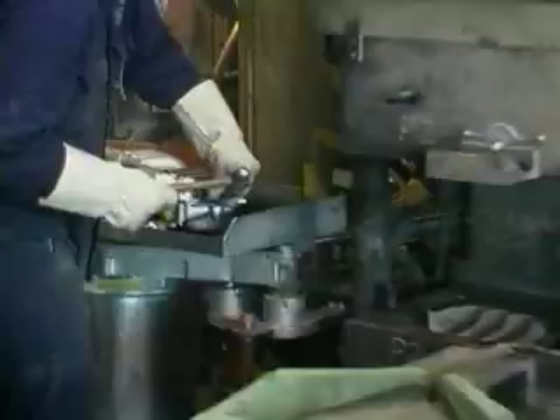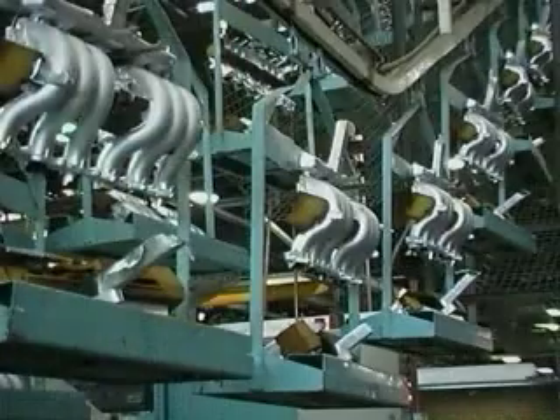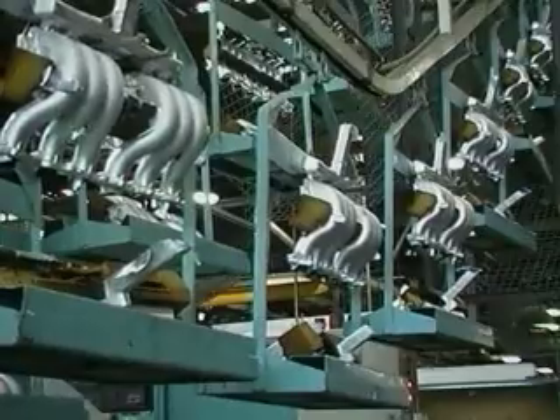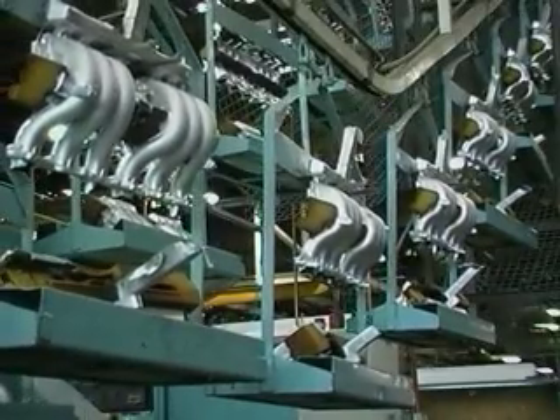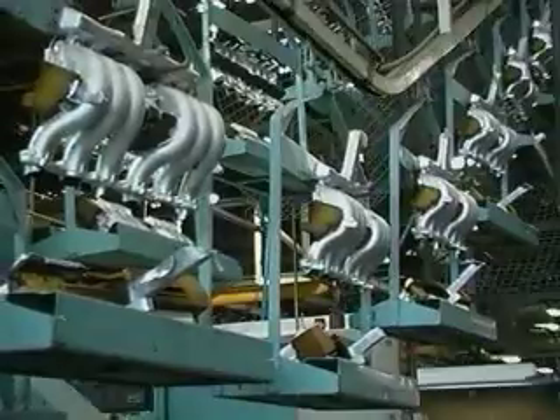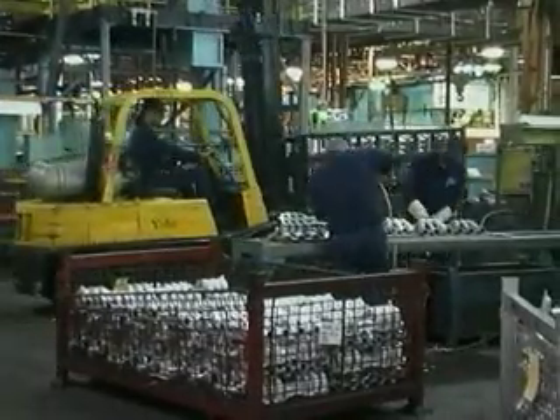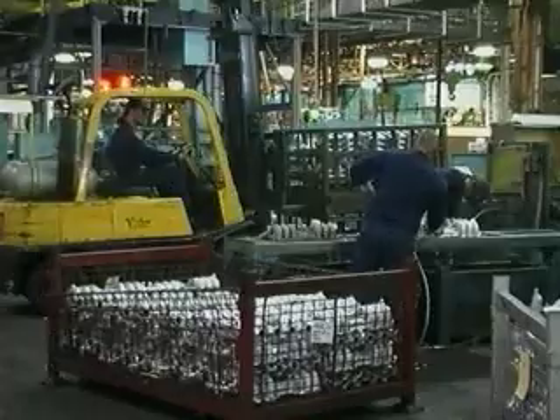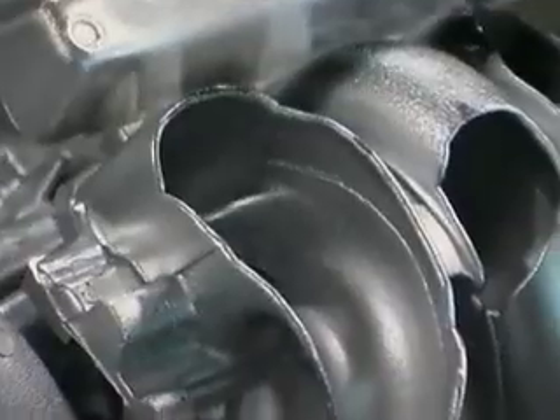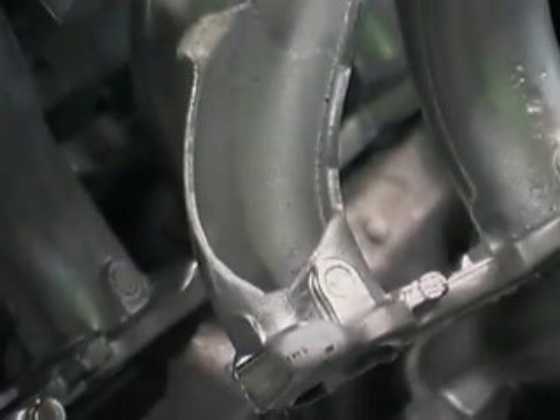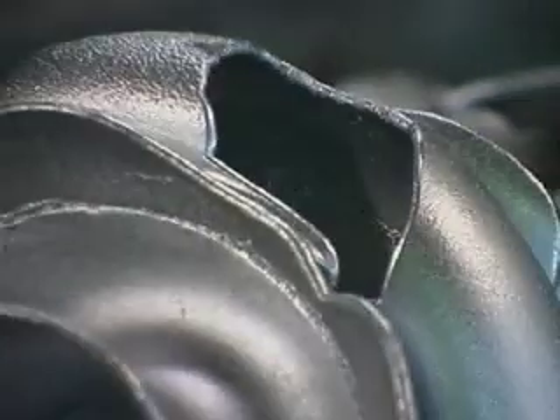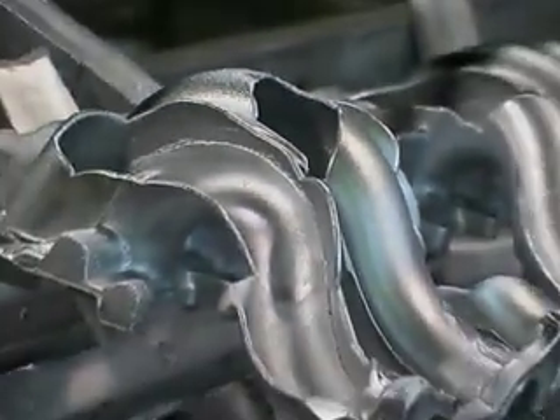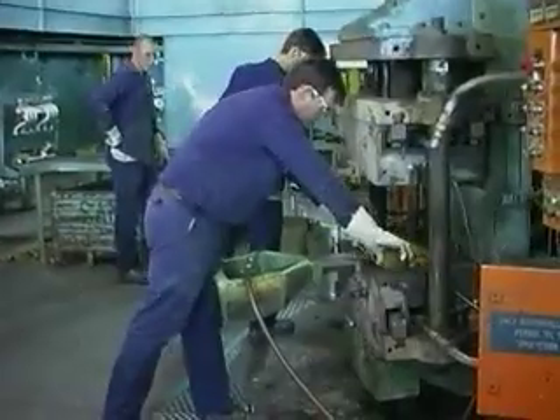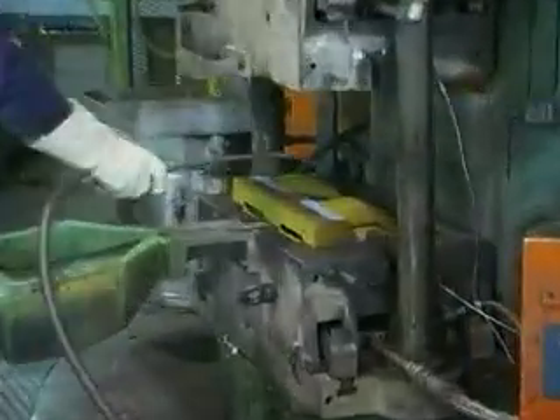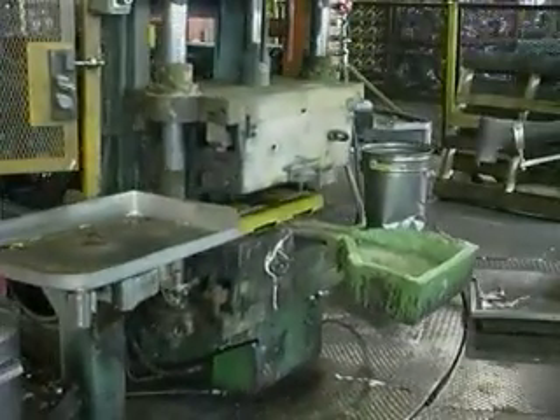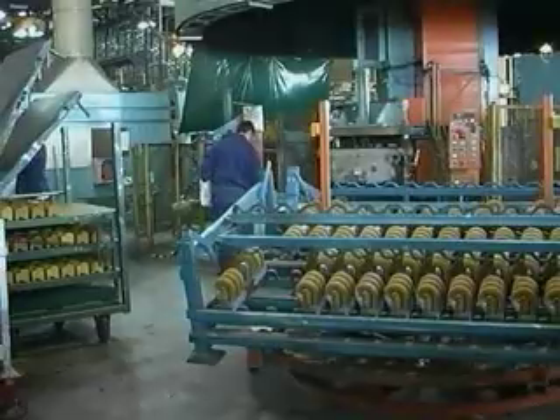The manifold is given an identification stamp and is put on a conveyor system to slowly cool for 2 hours, after which any fin formed where the die parts join is cut off and the runners and risers are sawn off. There's only a 3% scrap rate for these castings, the scrap being returned to the furnace. This defective casting shows the thin 3.5mm wall and the very complex internal shape of the manifold, which makes it difficult to cast. The cores to produce this internal cavity are loaded onto the die. The die closes and the process recommences. The production of these cores is an art in itself.